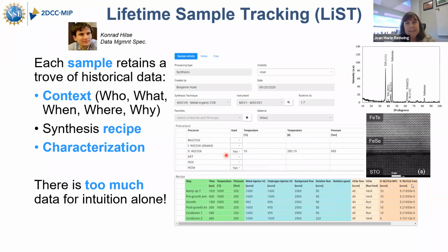And then I previously mentioned our LIST database. So Konrad Hilse has been the person here. He's our data specialist who developed LIST. And as I mentioned, it's used to capture all the information on samples that we produce in the facility. So this includes all the detailed recipes that are used for MOCVD growth and MBE growth, as well as all the characterization data. So all of the data, AFM, X-ray diffraction, TEM data, Raman photoluminescence data is all captured within the LIST database. And as I mentioned, we now have information on over 5,000 samples.